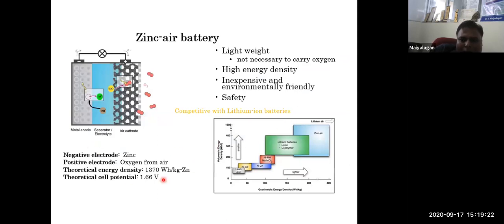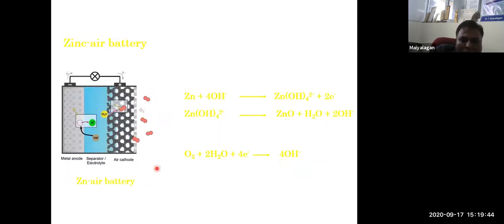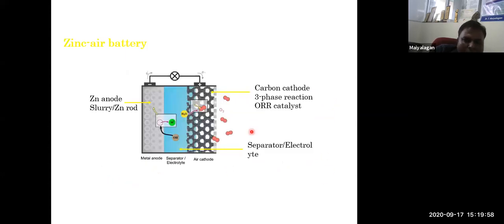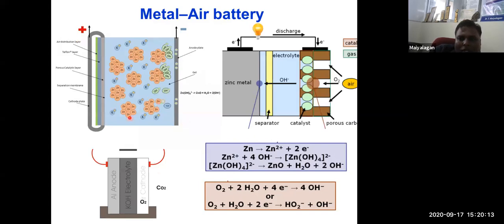Now, zinc air batteries, as I said, use zinc foil or zinc metal as the anode. It's lightweight. The negative electrode is the anode and the positive electrode is the cathode. The theoretical energy density is 1370, and the open circuit potential is even less than for lithium air batteries. The reaction taking place in the zinc air battery at the anode, in alkaline medium, is zinc reacting with hydroxide to form zinc hydroxide, and then at the air cathode oxygen reduction takes place. So you have a zinc anode or zinc slurry, an oxygen reduction catalyst, and a separator, now called the electrolyte, for the transfer to take place.